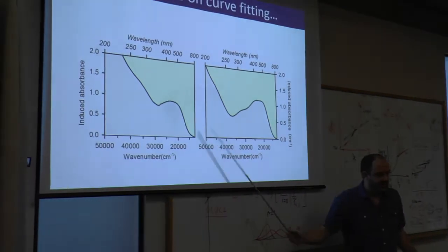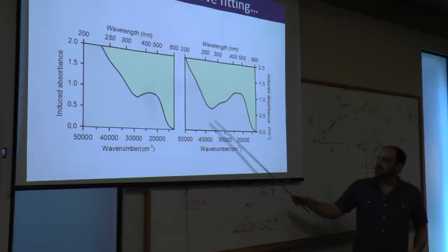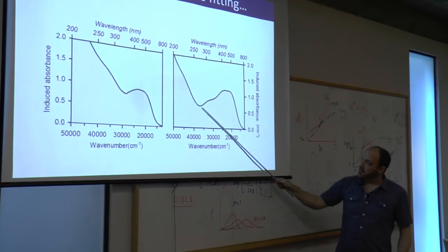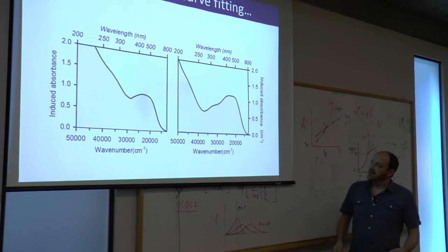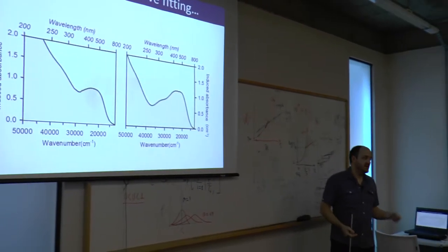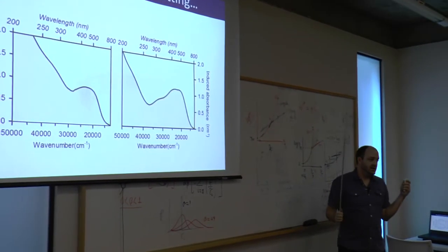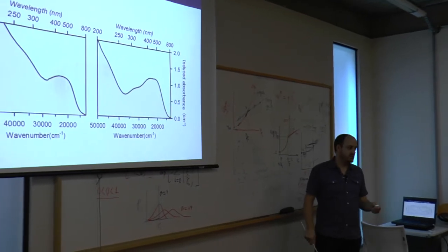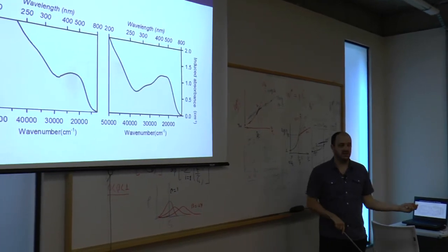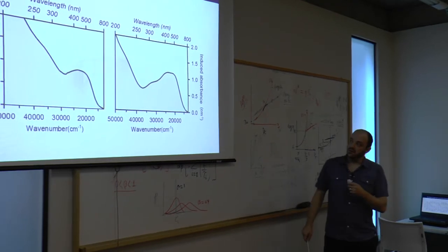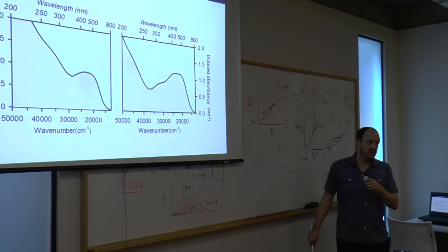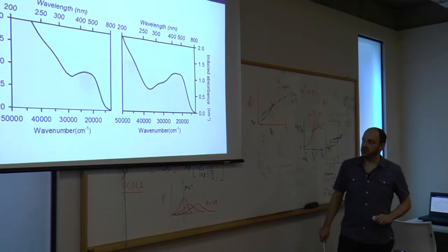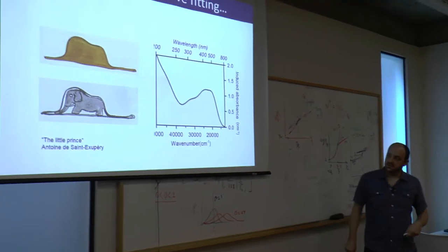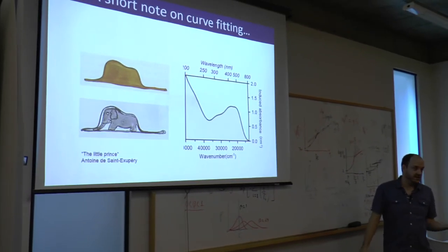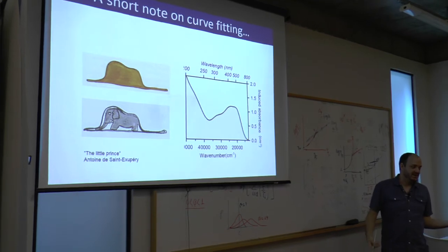So on the left side you have this nice broad feature, and maybe we want to put some curve fits under there. And you see, maybe you change the composition, you get a nice shoulder. When you have broad features like you have in glasses, it's really important to have a structural model in mind, that you test your model with the spectra. Because sometimes it could just be an elephant being eaten by a snake under there, and you don't know.